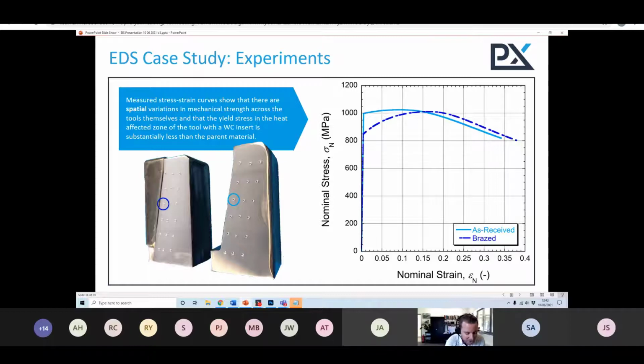So let's look at what we were able to achieve then. Well, first off, if you compare the equivalent locations from those specimens, you can see in the right-hand side in that graph that their stress strain behavior is very different. Their strength characteristics are different. And in fact, the brazing treatment or the heat treatment has led to a detectable drop in the yield stress of that material. So it's not as hard as it was. It's also not as strong as it was. Okay, and that type of detailed information simply cannot be picked up in a tensile test. Very, very challenging to capture that.